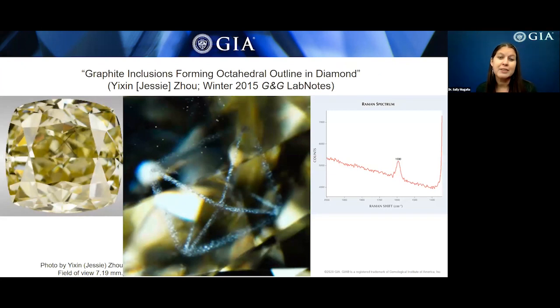This lab note is probably one of my favorites, as this stone has a surprise gift when it's seen under a microscope. GIA's New York laboratory received this 1.3 carat fancy brownish greenish yellow diamond. It was confirmed that it was a natural diamond with a natural color origin, and it contains this octahedral shaped inclusion that we show in the center. It was outlined by minute crystal inclusions along the junctions of the crystal faces.